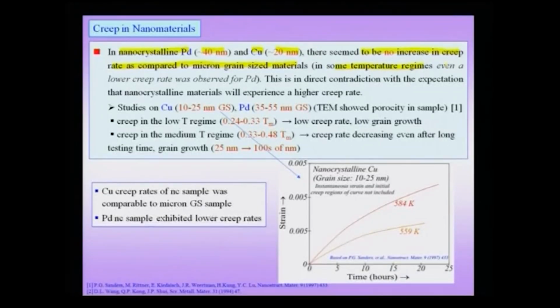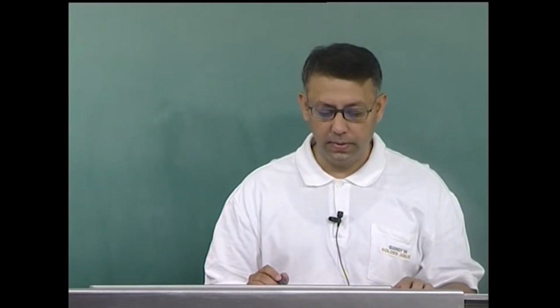And more surprisingly, in some temperature regimes, even a lower creep rate was observed in the case of palladium. So, this is in direct contradiction of our expectations, wherein we thought there was going to be enhanced creep rate, and therefore this is extremely surprising in the case of nanocrystalline materials and their creep behavior.